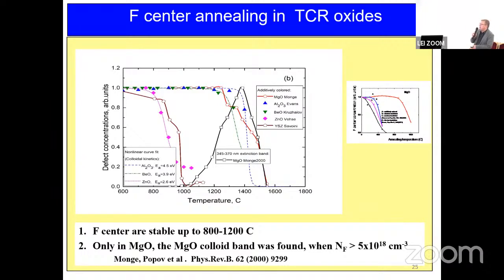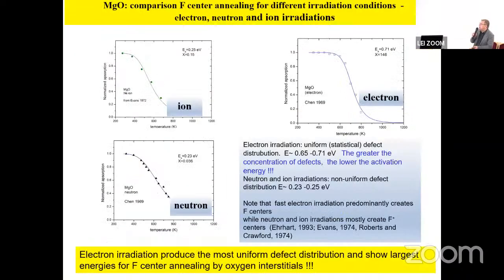First of all, we characterized materials in which centers were created by thermochemical reduction. So we evaluated the diffusion energy for such types of defects from this data using our model. And then we started to work with irradiated samples.